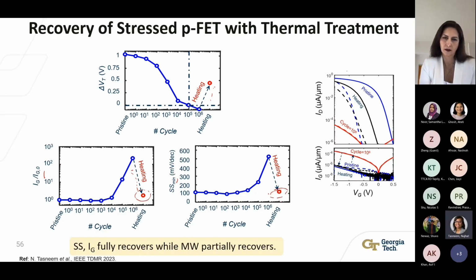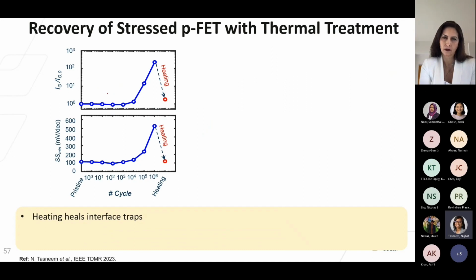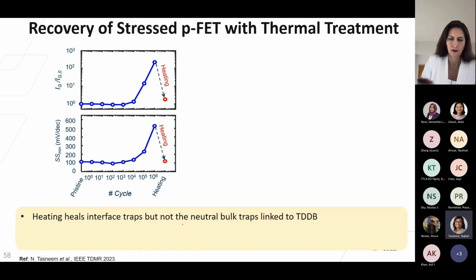So to summarize, the results show that gate leakage and subthreshold swing keep on degrading with fatigue cycling, indicating interface degradation. However, after thermal treatment, both these values fully recover and go to their pristine state. So this indicates that heating can actually heal the interface traps. However, the older paper also showed that in MOS capacitors, heating cannot heal the neutral bulk trap that is related to the time-dependent dielectric breakdown.